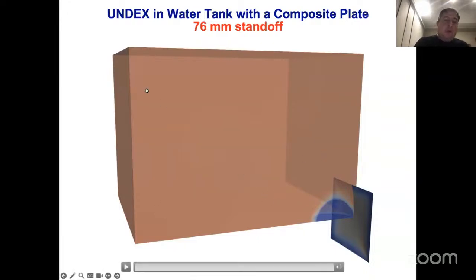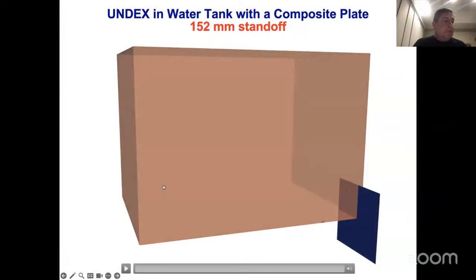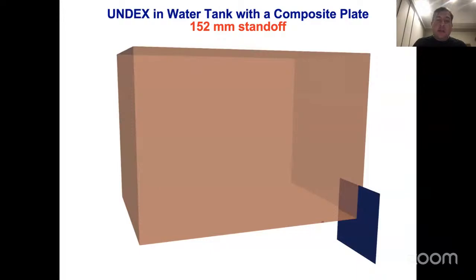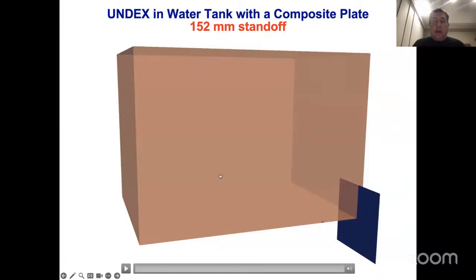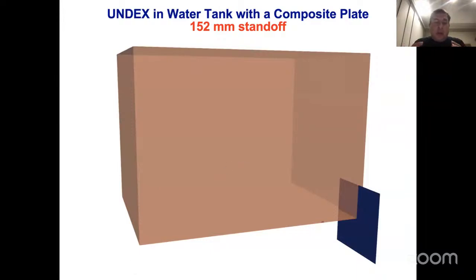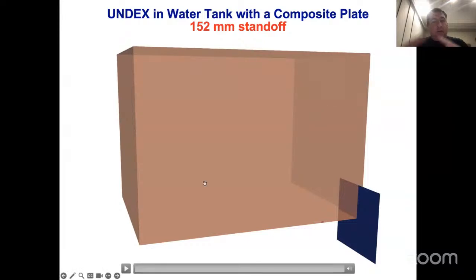The shock in water travels on the order of microseconds, okay? While the expansion and the collapse of the bubble is milliseconds, right? So there's 10 to the 3, 10 to the 4 orders of magnitude of time scales that you need to handle. This is the biggest challenge in these calculations, okay?